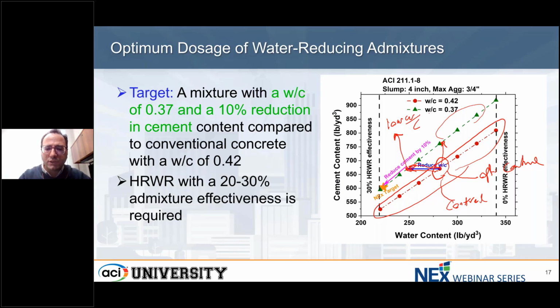And the next step, we're going to reduce the cement for this low water cement ratio system by 5% and by 10%. So we're going to have a mix here with 5% reduction in the cement content and 10%, which is our goal, as shown here with this next target orange star sign. So if we want to get from here to this part of the graph, we're going to need a very effective high range water reducer in order to do this. That's why we are using high range water reducer instead of normal range or mid range, because that's not going to work for this type of system.